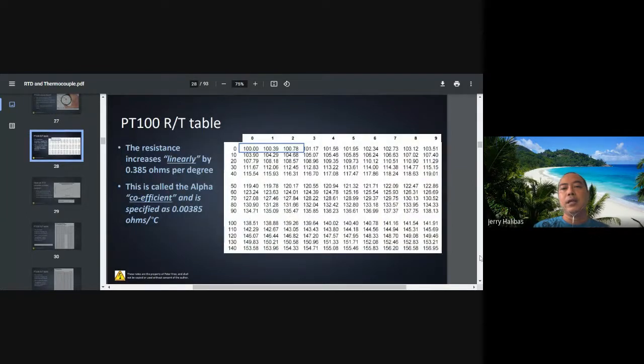Okay, so we go now to the table. This is the table for a PT100. Notice at 0, the 0 column and 0 row, it's 100 ohms. In the first column, 1 degree centigrade is 100.39, 2 degrees centigrade is 100.78 ohms, until 9 degrees centigrade, where you're expecting 103.51 ohms. At 10, it is 103.9. At 20, 107.79. So this table is very important for calibration. For calibration, you need to have this standard table. And this is in reference to the temperature coefficient, which is 0.00385, or the alpha.